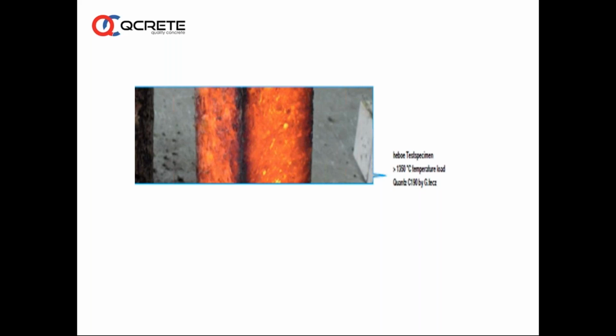Fire resistance is also significant. Fire resistance is achieved, okay, where 1350 degrees centigrade temperature load is withstood by concrete with a strength of 190 MPa.